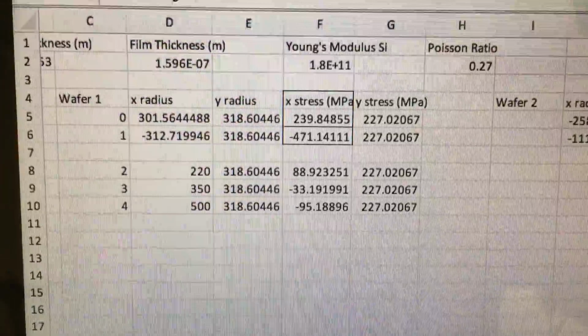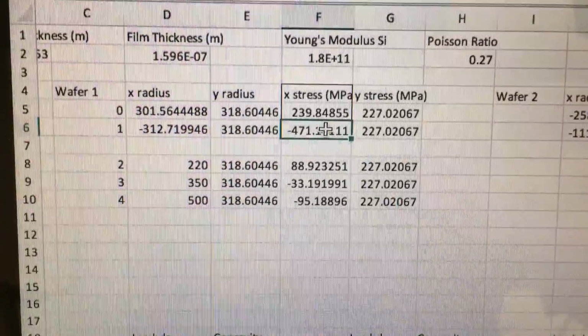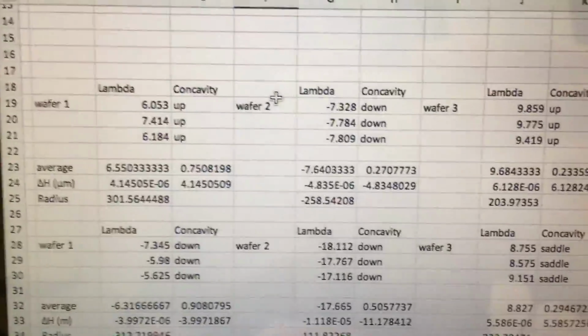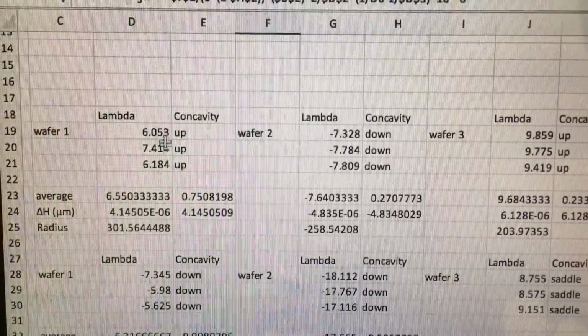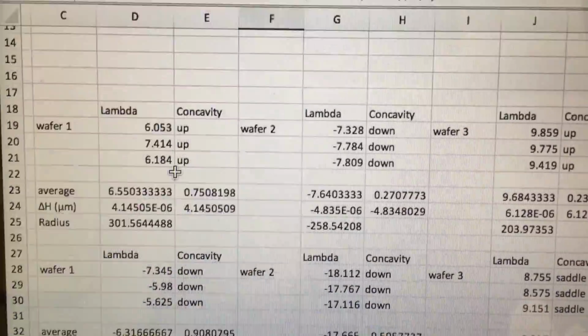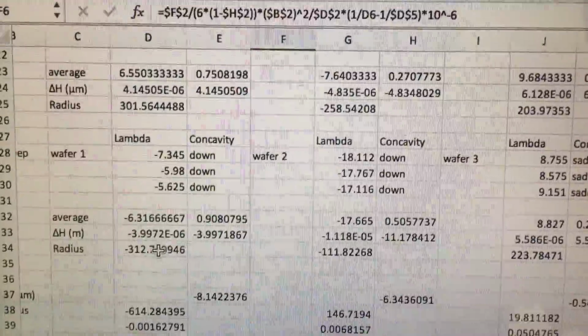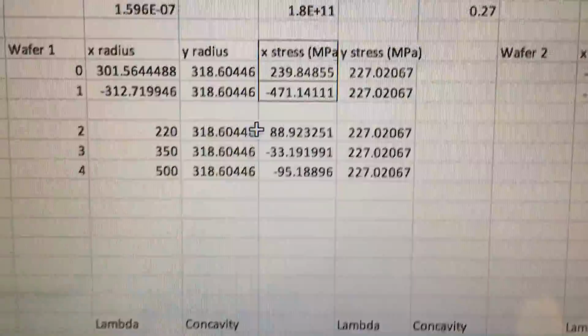Here's where we calculated the final stress value right here from our raw data here. These are the displacement values in terms of lambda, and we ended up with radius of curvature measurements here, which we then calculate up here.